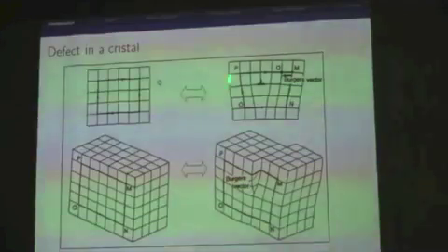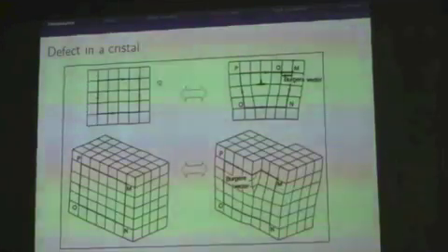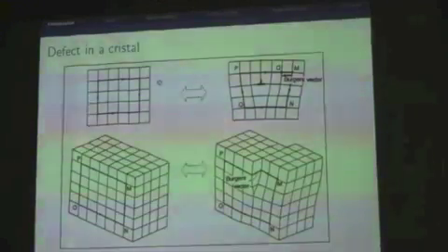But if this guy makes four steps from Q to N, he does not close the parallelogram. If he makes the same number of steps, he goes only from P to Q. So there is a small vector which closes the parallelogram, from M to Q. This situation can be seen also in a screw dislocation, where the same process can be performed, and the picture shows this phenomenon.